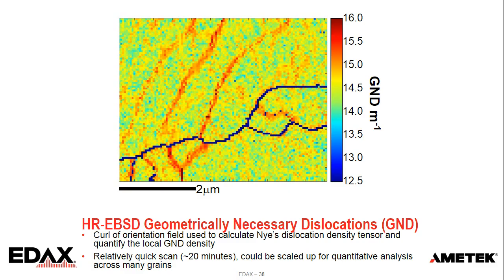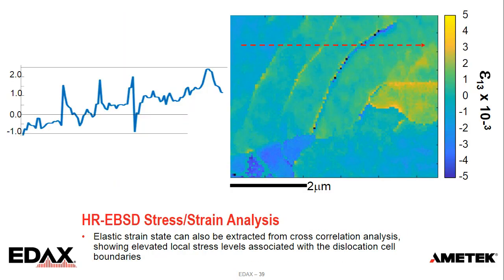And once we have that, we're also able to look at the stress and strain that comes out of that cross-correlation analysis. This just shows a profile line horizontally going across some of those cell walls, and we can see the stress state going along that. So we see where it can go from a state of compression to tension along those different parts of the dislocation structure. And so that's, I want to say it's relatively new, but it's been around for a while now, more information we can extract from the EBSD patterns.